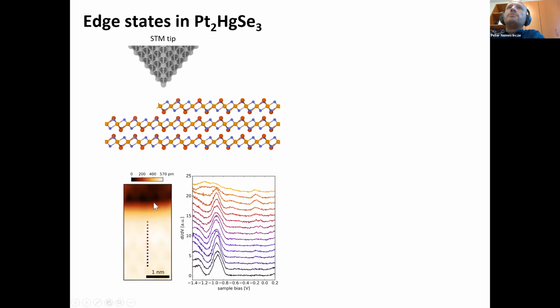And indeed, if you find one of these monolayer edges, which you can see here, and you do tunneling spectroscopy, getting closer and closer to the edge, you can see that the gap here starts to fill as you approach the edge of the crystal. So this is a very good indication that you have some states appearing in the band gap.